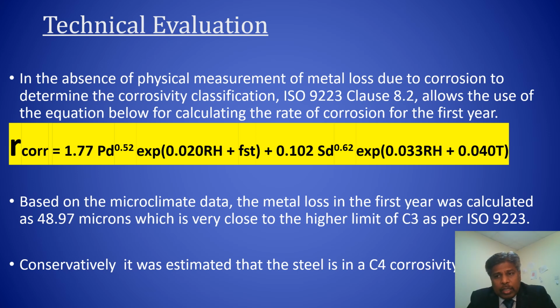So when we did the calculation, as shown in the previous slide, it was coming only to about 49 microns per annum. And typically, if you follow ISO 9223, which is also referred to in ISO 12944, any environment that has less than 50 microns would be classified as a C3. But again, this was on the very high side of the C3 limit, which is up to 50 micron per annum. Our engineering judgment was that the steel within the building would be exposed to a C4 internal corrosivity category as per ISO 12944 or even as per ISO 9223.